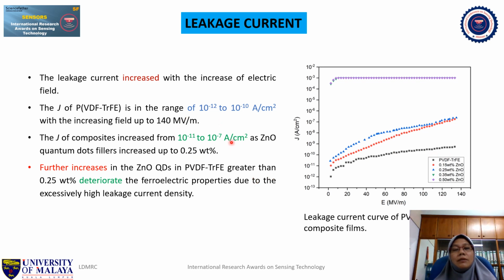So the leakage current increased up to 10 to the minus 11 to 10 to the minus 7 ampere per centimeter square, as zinc oxide quantum dot is increased up to 0.25 weight%, as shown in this figure here. So when we increase zinc oxide quantum dots composition to higher than 0.25 weight%, we can see that the leakage current has increased tremendously, which deteriorates the ferroelectric properties due to the excessively high leakage current density.